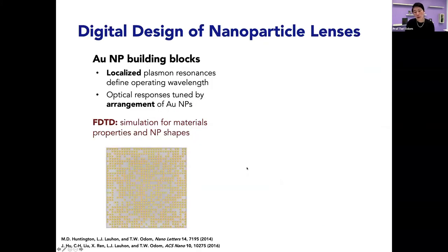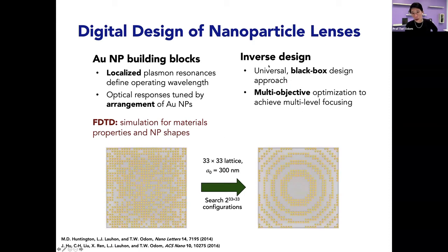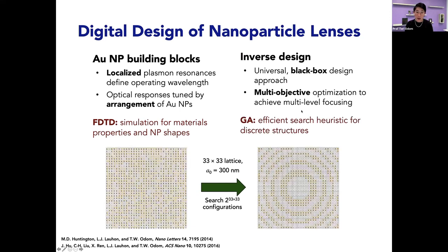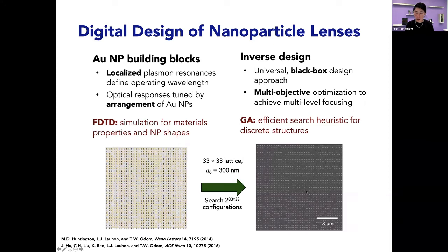Then we extended this from hole arrays to these nanoparticle arrays, because the nanoparticles support localized plasmon resonances. And if we control the shape of these, we can control the operating wavelength. But then, of course, it became more complicated because we need to use finite difference time domain simulations. So we had this inverse design where we used a black box approach and a multi-objective optimization. It's not simple, and it took a lot of time, but at the end of the day, you can get imaging, or actually focusing, at three different colors of wavelengths, each of them defined by the localized surface plasmon of the particles.